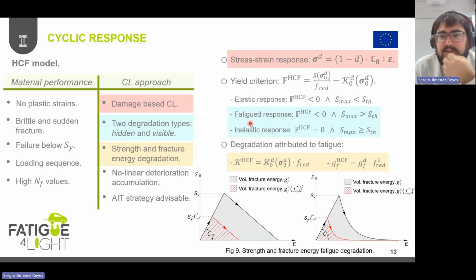It's exactly the same, where we somehow initiate the inelasticity process in a hidden, non-apparent way for stresses which are, for maximum stresses which are above the fatigue limit of the material, but we still satisfy the yield criteria described through this expression here.